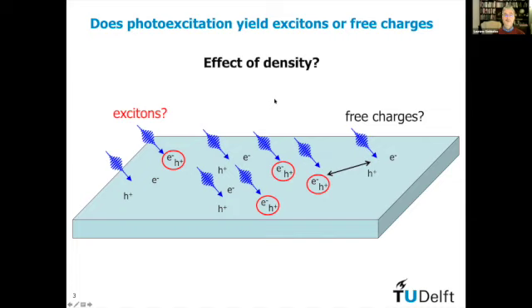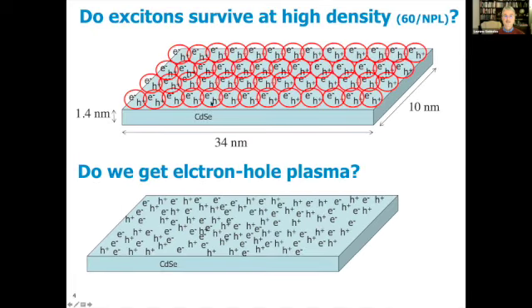And what we wanted to know is, if you photoexcite these nanoplatelets, do you really get excitons or do you get free charges? And in particular, what is the effect of the photoexcitation density? So if you fill up such a nanoplatelet by producing many excitons, by absorbing many photons in one nanoplatelet, do you get stable excitons that are sitting next to each other? Or do electrons not know anymore to which hole they belong, and do they spread out and move all over the place like the holes do? And you get a sort of metallic system, which is known as an electron-hole plasma.